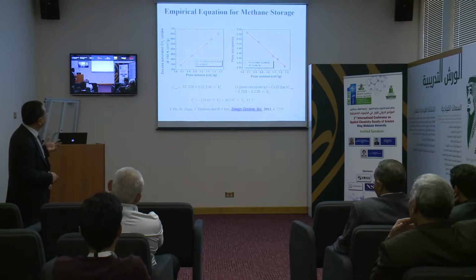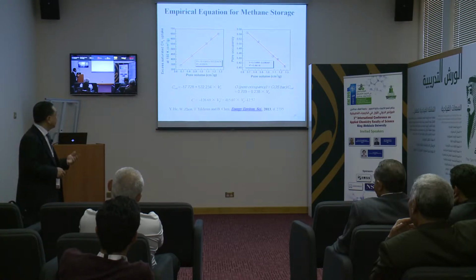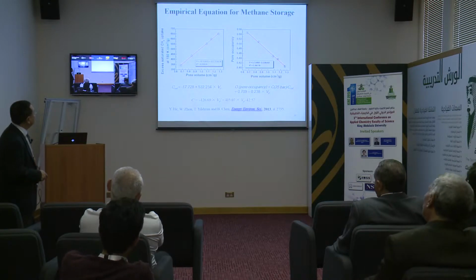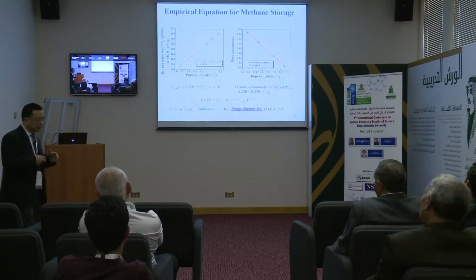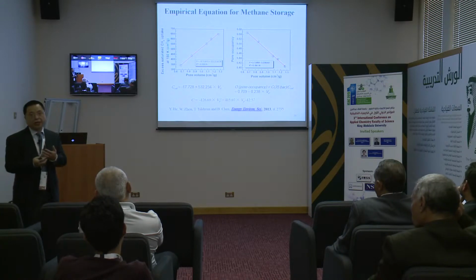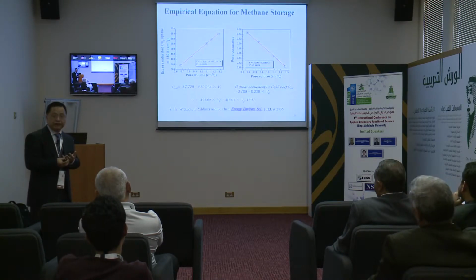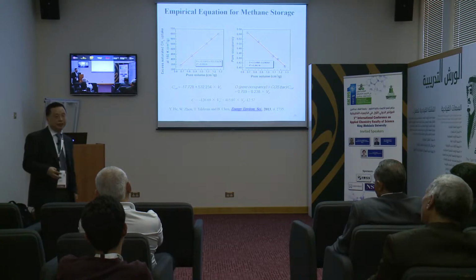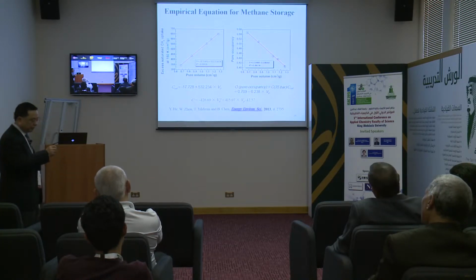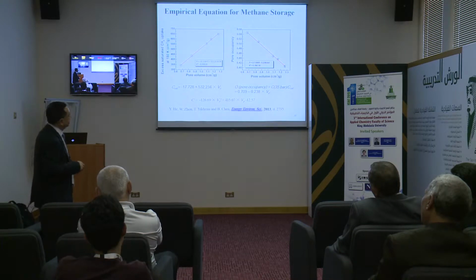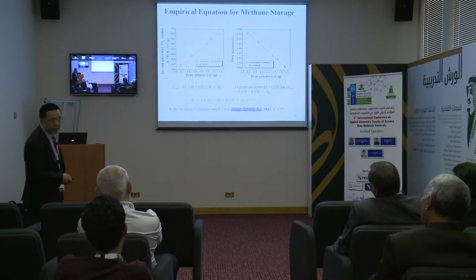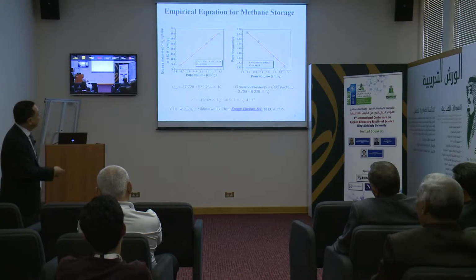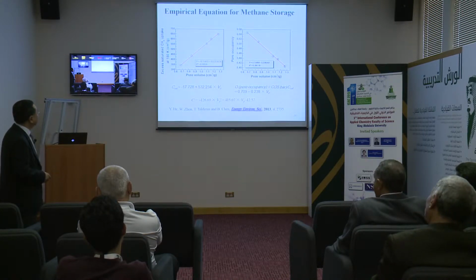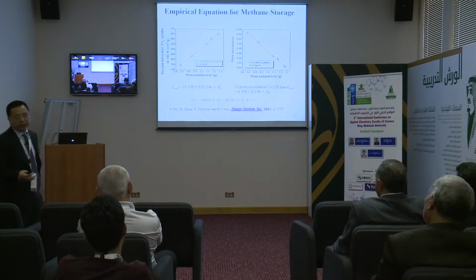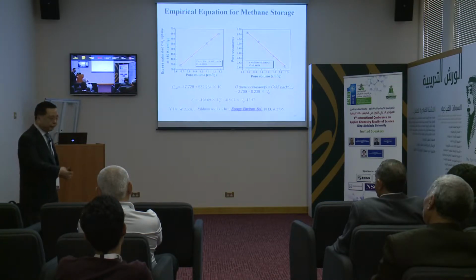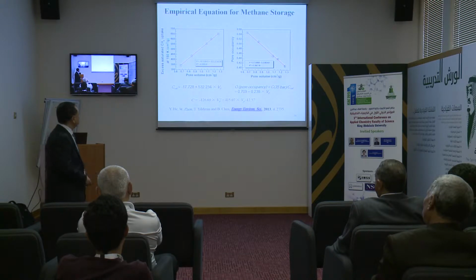And nowadays, it would be good if we can establish an empirical formula for methane storage. The reason is the high pressure adsorption data sometimes are not reliable because of the sensitivity of this kind of instrument. In fact, only a few reliable instruments are available right now. And also we can easily get porosity from adsorption studies. So if we can make some prediction from this data, then we will facilitate our screening. We can screen some materials first before we do detailed studies.